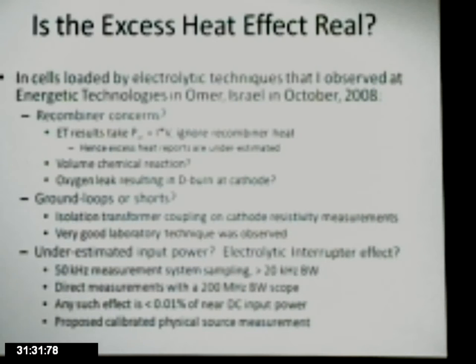Now, this underestimate of the input power, this electrolytic interrupter effect, okay? Again, it was about 50 kilohertz actual measurement system sampling, clearly greater than about a 20 kilohertz true bandwidth. Direct measurements with the scope showed no effect. In fact, if you just assume that what was probably antenna pickup on the scope was actually correlated and an electrolytic effect, then it would be like a 0.01% correction to the applied power. But again, it was generally uncorrelated antenna noise, so it was probably much, much less than that.